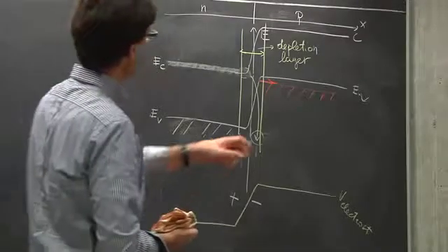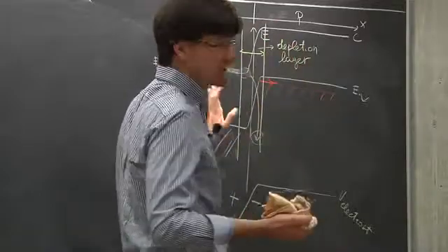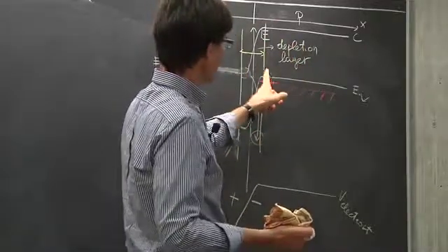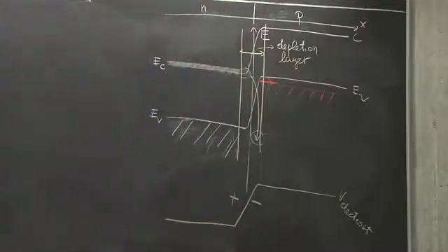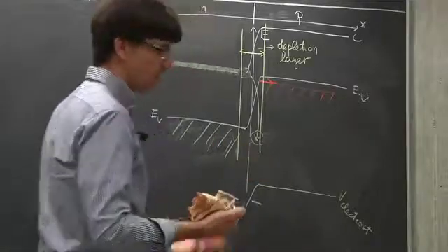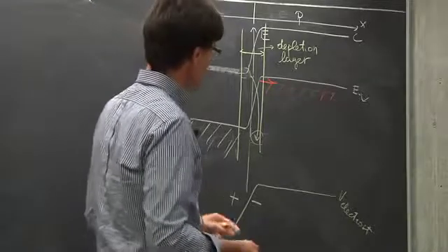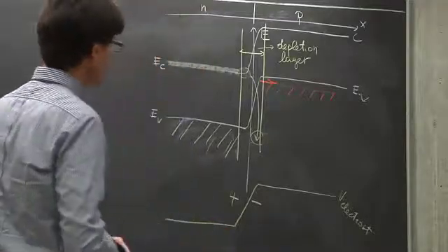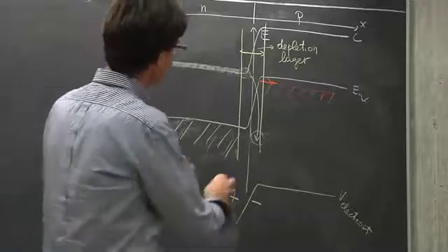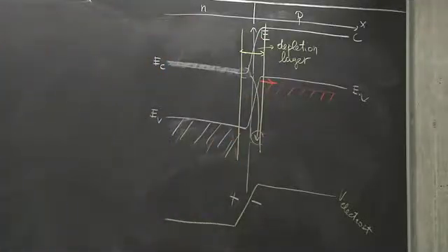The second consequence is that you form a layer in which there are no charge carriers, no electrons and no missing electrons on the other side. It's a very narrow range. It's typically of the order of much less than a micron. It's typically a few hundred angstroms, the depletion layer. But it's a region of space in which there is no charge available, and there is a considerable shift of the band structure. Okay? Any question about this? Do we all agree that this is what's going to happen?